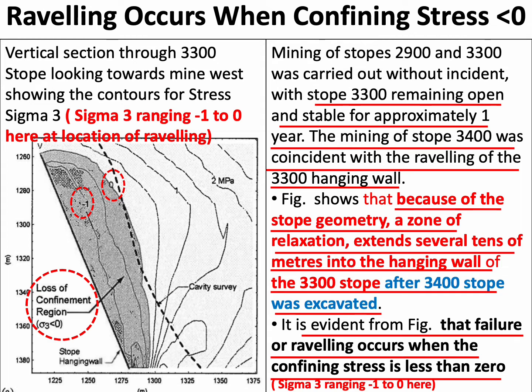Mining of stopes 2900 and 3300 was carried out without incident, with stope 3300 remaining open and stable for approximately 1 year. The mining of stope 3400 was coincident with the raveling of the 3300 hanging wall. The figure shows that because of the stope geometry, a zone of relaxation extends several tens of meters into the hanging wall of stope 3300 after stope 3400 was excavated. So what had happened was that, having withstood all the stresses that were there before stope 3400 started to be excavated, stope 3300 stood for 1 year.